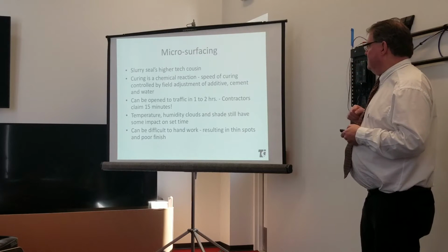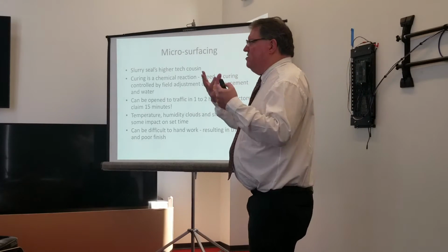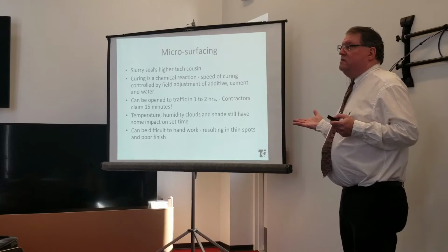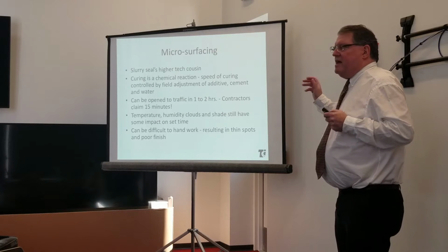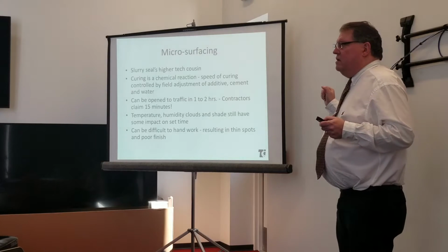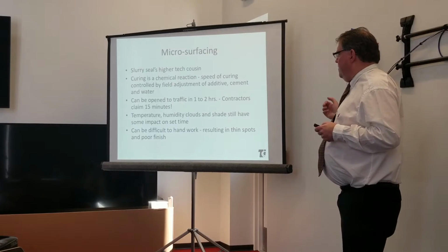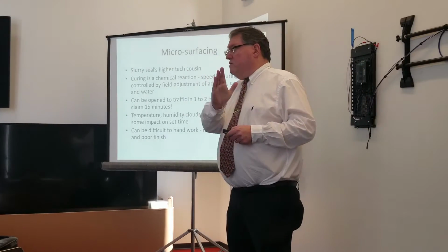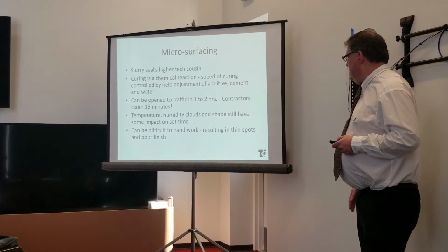Microsurfacing is like a high-tech slurry seal. There's a chemical reaction that happens in the cure, so it's actually going to be driving that water out. And I'd say 1 to 2 hours opening time. Your contractor's going to say, well, I can get that open in 15 minutes. Right? And so good weather, we're being really aggressive on it. Yeah, we may be able to put cross traffic across an intersection after we pull an intersection in that 15 minutes. But generally figure an hour or two.